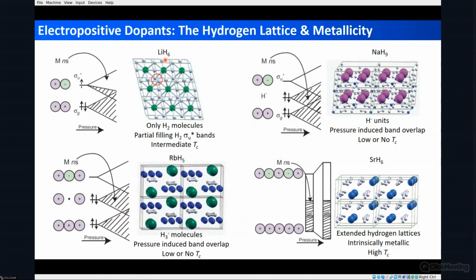So if we have only H2 molecules in the system, in the stable systems under pressure, one example that was predicted is this LiH6. The reason why you get metallization is the electropositive element is going to be donating electrons into the H2 antibonding bands, and so these types of systems are metallic already at 1 atmosphere, though they are not going to be stable, and superconductivity can occur with usually relatively decent TCs, but nothing approaching room temperature superconductivity.